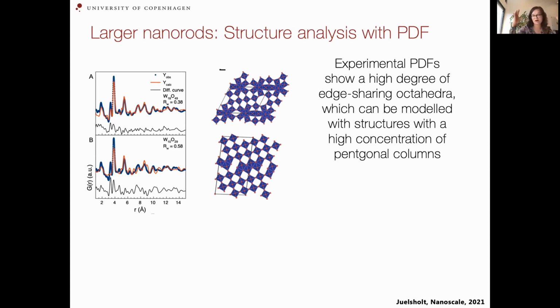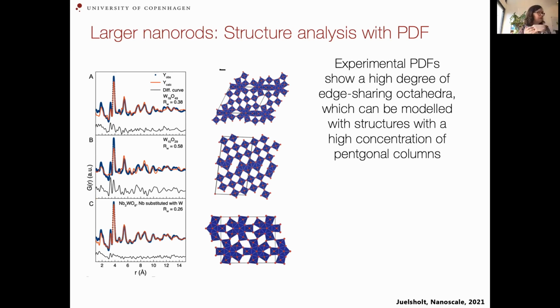And we went through a lot of different structures, also including elements with similar chemistry, for example, niobium. And we found out that we could actually get a nice description of these nanorods if we took a niobium tungstate structure, which has this structure here, and substituted niobium with tungsten. So we just use a structure from a slightly different chemical system. And then we can describe this in much more detail.